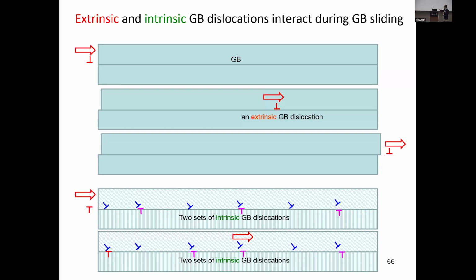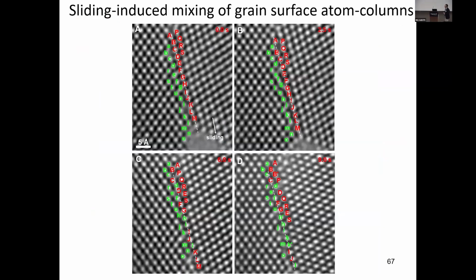So if you want to produce this sliding, you need to inject this extrinsic grain boundary dislocation, gliding through this boundary and interacting with the intrinsic grain boundary dislocation. And so these detailed complex processes can now be clearly resolved through in situ experiments coupled with our atomistic simulation. More interestingly, we even discovered lots of unexpected processes that go beyond what we can achieve at this stage through direct molecular dynamics simulation.